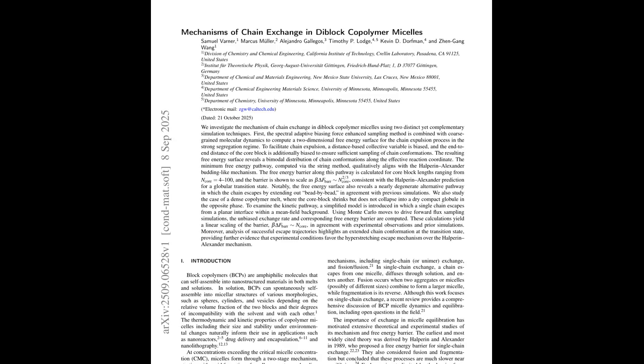This work approaches the question by employing molecular dynamic simulations combined with advanced free energy calculations to map the chain escape process. The authors use collective variables related to the chain's configuration, such as junction point positions and end-to-end distances, to construct two-dimensional free energy surfaces and minimum free energy paths.